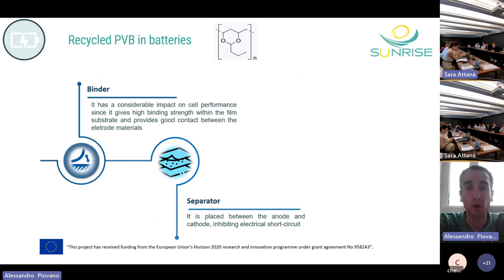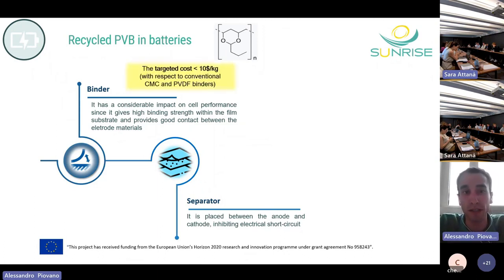As for our role in the Sunrise project, that is to try to use the recycled PVB in batteries, we are exploring the possibility of using PVB as a binder, which has a considerable impact on the cell performance because it provides the strength within the electrode substrate and provides a good contact between the electrode materials. In this case, according to our market research, our target cost is lower than $10 per kilo in order to be competitive with conventional binders such as carboxymethyl cellulose and polyvinylidene fluoride.